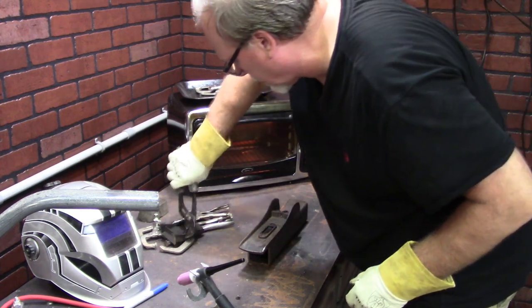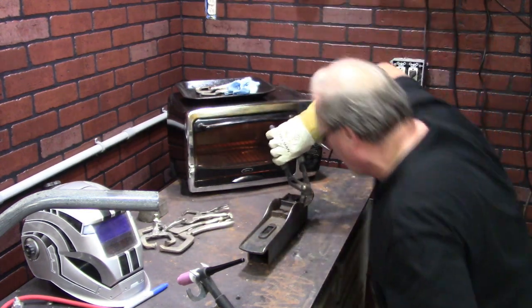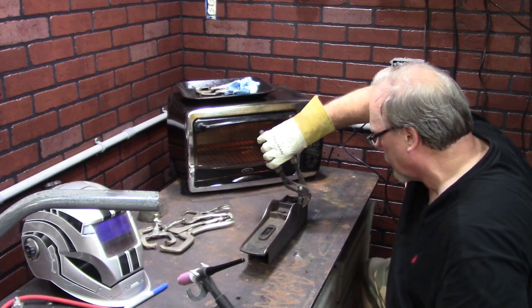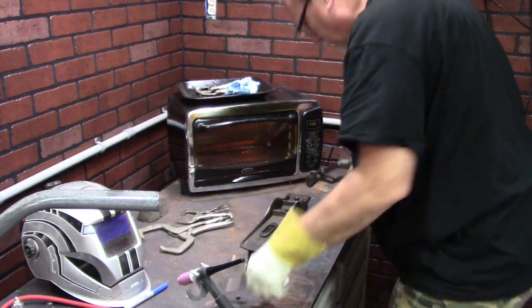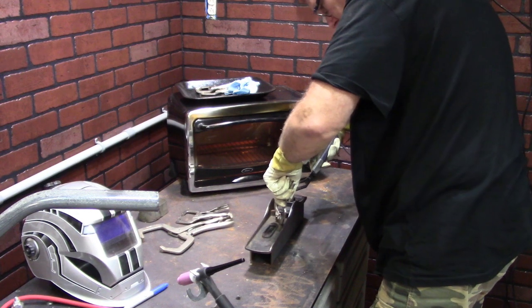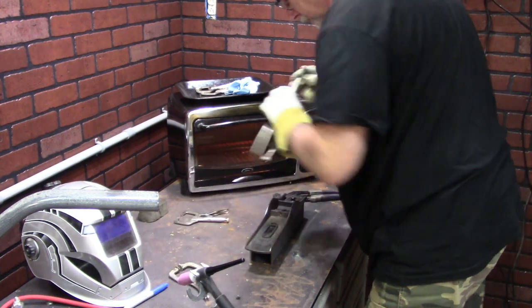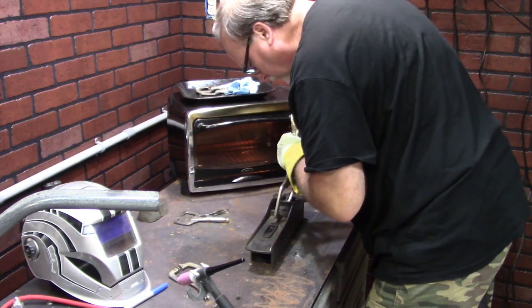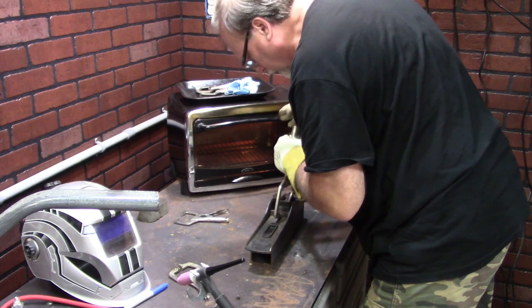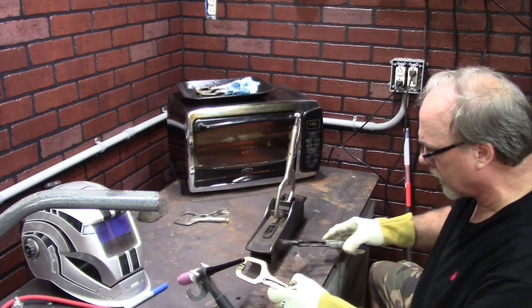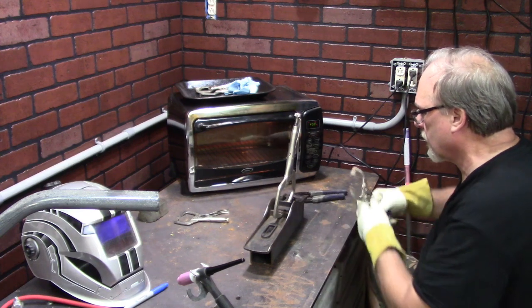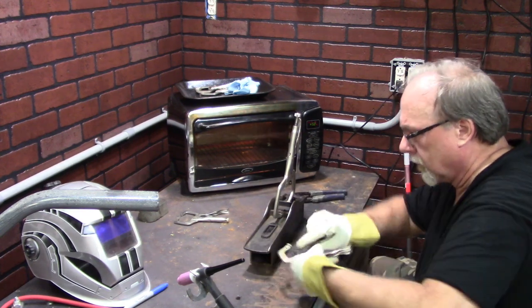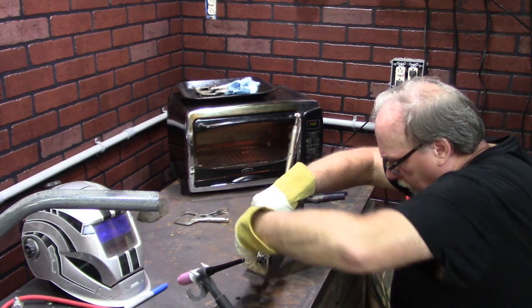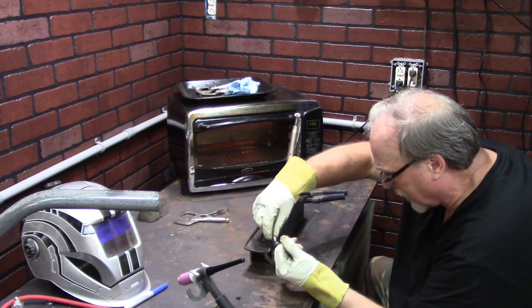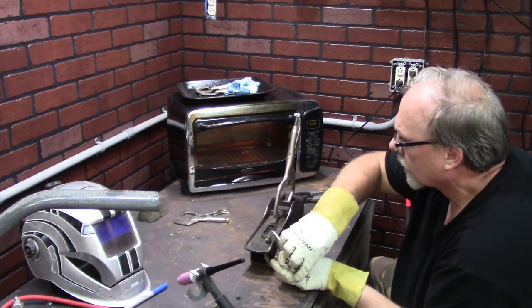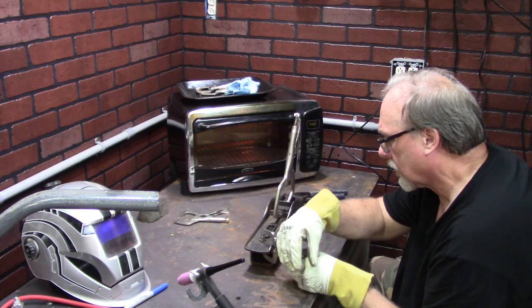Here we'll just set it up in the jig, and I'll use my larger vice grips and clamps, and I'll pull it together on two machined surfaces on the inside of that plane. That'll lock those two fracture lines together perfectly. And then I'm going to lock the ends of the casting down to the steel. This way everything is going to be as flat and as true as possible when I weld it.